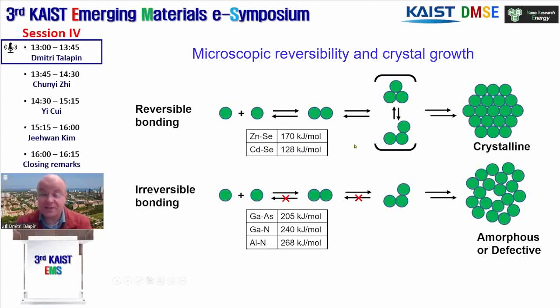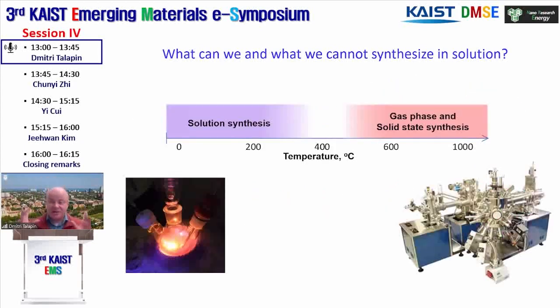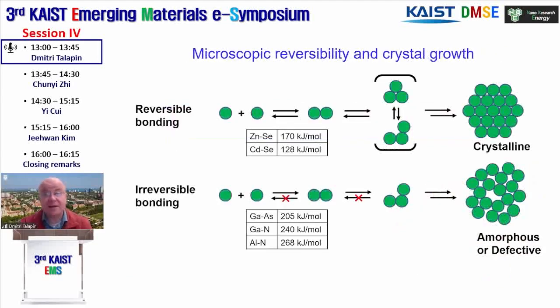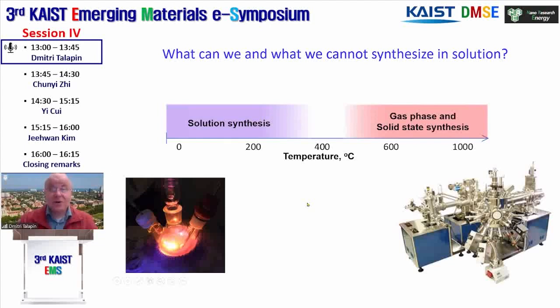If you look at the bond dissociation energy of materials that we can easily synthesize by solution chemistry, such as cadmium selenide or zinc selenide, examples I've shown previously, and compare it to the materials that we cannot synthesize by solution chemistry, or couldn't after several decades of effort, we will find that gallium arsenide has much stronger bonding, as well as gallium nitride. So in traditional MBE or CVD chemistry, this problem is addressed by going to high temperatures. We use k_B T thermal energy in the system to break chemical bonds and establish reversibility. So overall, it creates an interesting situation where we have two ecosystems for chemical synthesis.